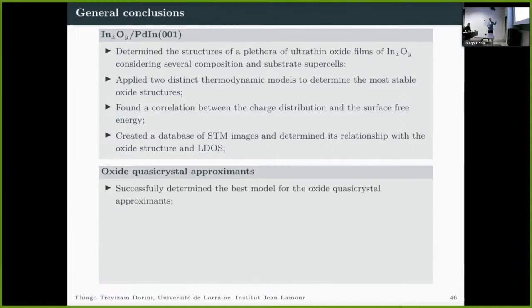For the first part, we have determined which were the most suitable models to analyze the oxide quasicrystal approximants. We have seen with the COHP calculations that the titanium atoms are bonded strongly to the metallic substrates, and this may lead to the stabilization of the approximants in general.